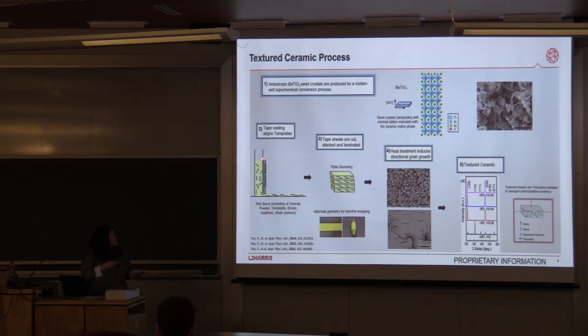And what you're going to do is tape cast it. So you're going to run it under a doctor blade. Down here is a carrier film that's going to flow through, and your seeds are going to align in this one direction. Here is what I've actually brought today, and I'll pass it around. Usually when we tape cast, we have a large roll that's hundreds of feet. And in the second step, we cut this. So this is actually a ceramic binder, templates, all of that in here right now. So I'll pass some of this around.